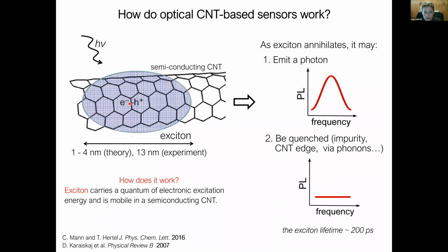And their electron and hole, these electrostatics should be of importance in such a system. So the way the exciton emits light is that the exciton has to annihilate, it just needs to disappear, go back to ground state, and it either emits light or it doesn't emit light. There are two ways it can relax down.